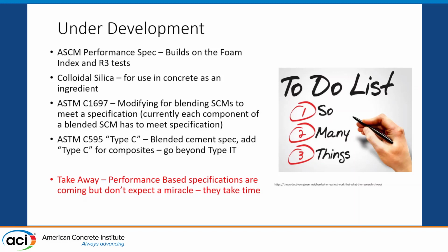We're working to modify an existing standard, C1697, for blended SCMs. So you could take a fly ash and a slag or a different pozzolan, 2 different materials, put them together and meet it. But right now it says each one of those individual materials in your blend has to meet a standard on its own. So if you had a fly ash that didn't meet one requirement, say the fineness or loss on ignition, you couldn't use it in that standard as a blend. We're trying to change that, open it up so the final product meets the spec, not the individual ingredients. And that will open it up to more accessible use of a number of materials.